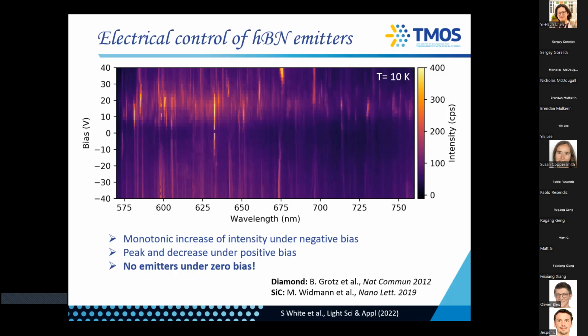At the negative voltage, you see an opposite effect. You see that the emitters just gradually turn on. So this one is on brighter and brighter, etc. Now, here, there are two important things. One is that we don't know which wavelength we are imaging a priori. We just put a sample with many, many emitters, and then we turn the voltage on. And number two is that, remember that every emitter turns on at a different voltage, but we don't know which one will turn on at which voltage. Okay, so we can't control that. It's all the result of the actual experiment.